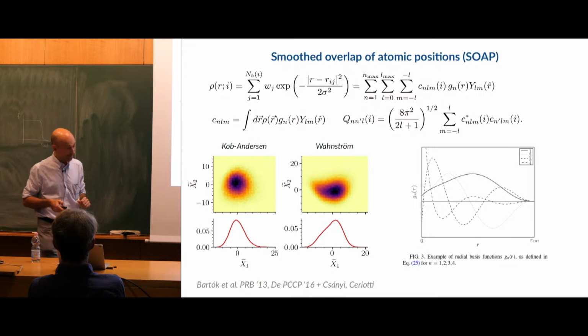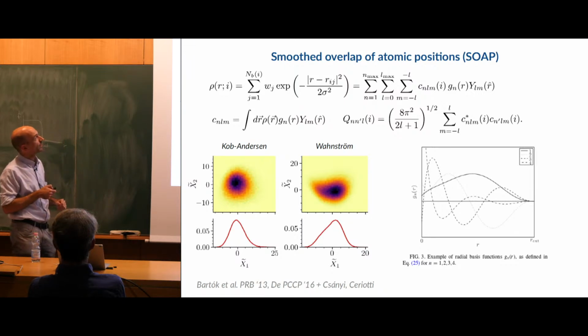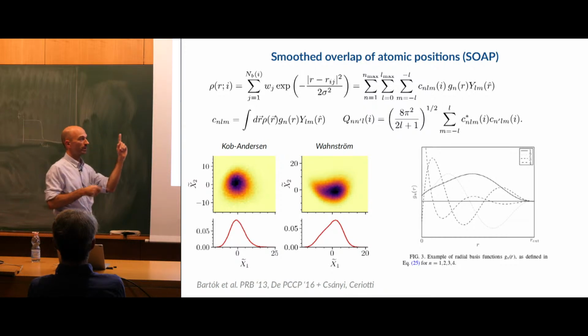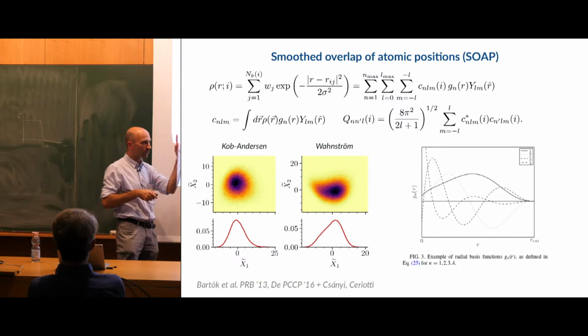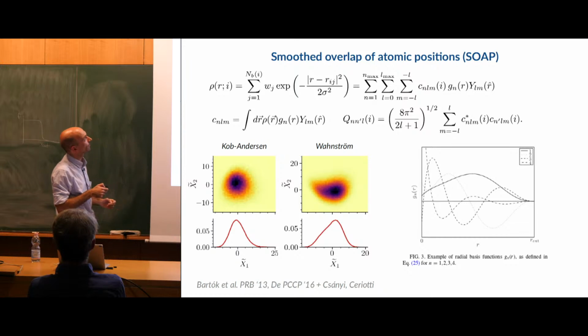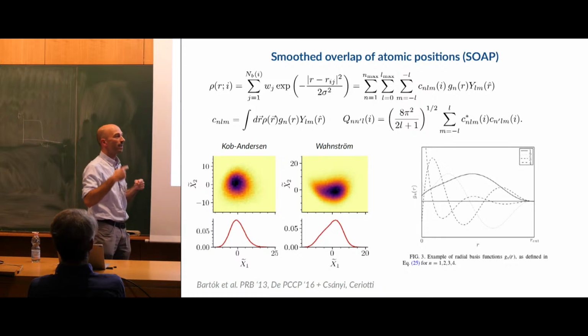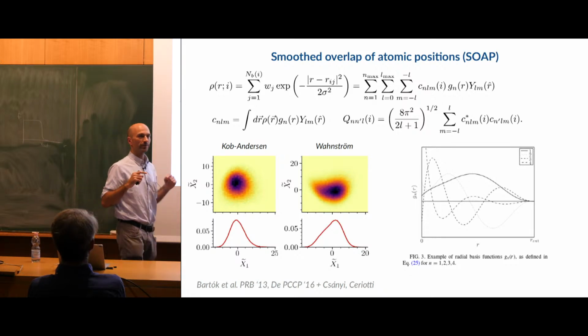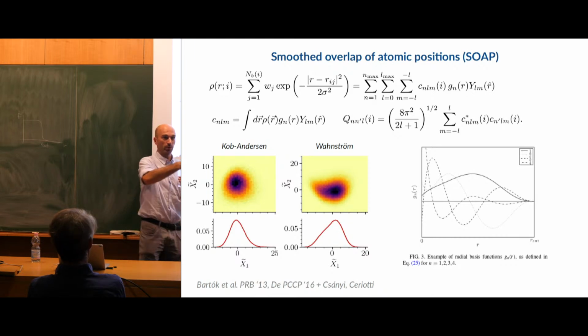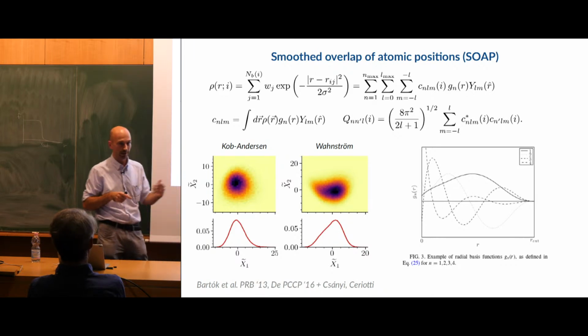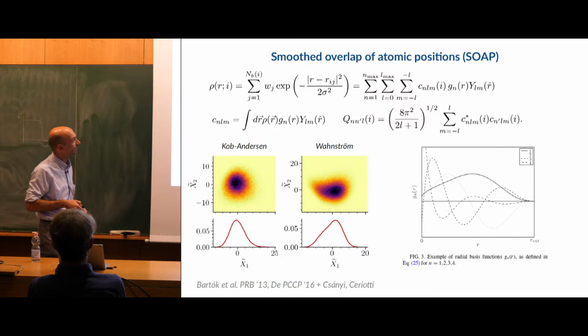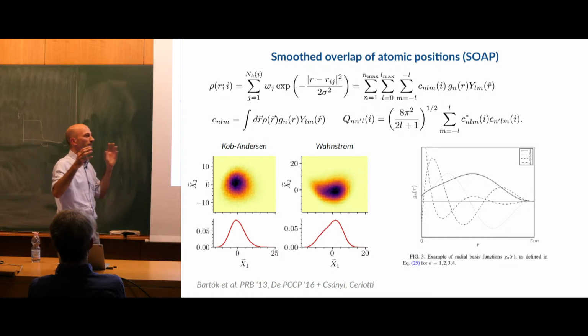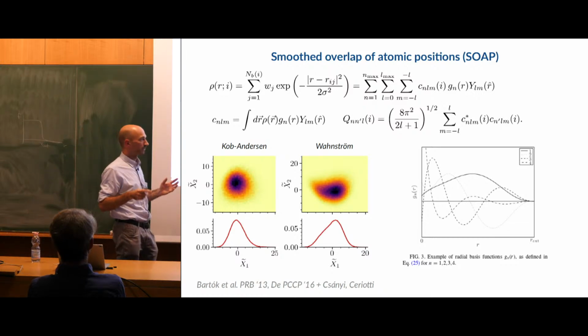So SOAP starts from a smooth description of the local density. The local density of each particle is microscopic, and it is smeared with a Gaussian of width sigma, okay? And then this smoothed density is expanded in spherical harmonics, plus they keep into account the radial dependence of the bond order with an additional basis, a radial basis, g_n(r), which allows you to keep much more information in your descriptor.